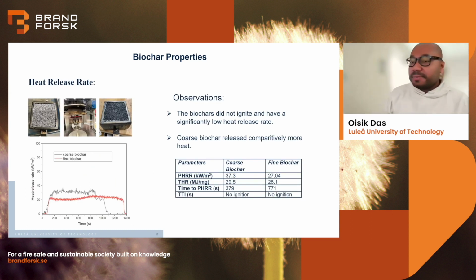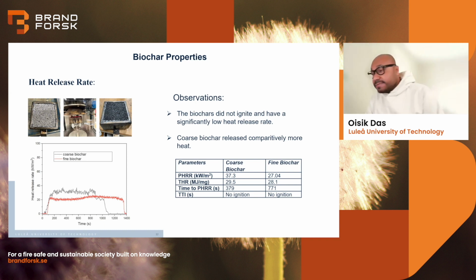Then this is where the fire testing comes. So before we even test the concrete in fire, we have to understand how biochar reacts under fire. So we have used a cone calorimeter. The principle of cone calorimeter is that almost any material in the whole world, when it burns and consumes 1 kilogram of oxygen, releases about 13 megajoule of energy. So every material, after consuming 1 kilogram of oxygen, will release about 13 megajoule of energy. And if we can calculate the flow rate of oxygen, we can calculate the energy released. And from that, we can get a host of reaction to fire information in cone calorimeter.